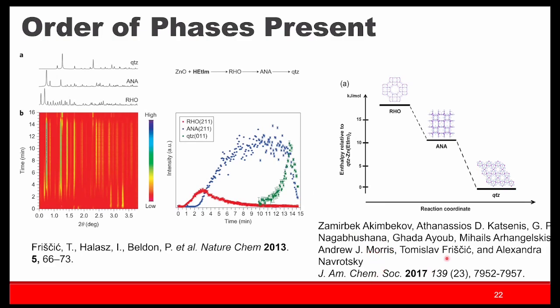And we did a bunch of calorimetry and thermodynamic calculations, which basically show that we're actually going down in energy. So we're starting at the least stable phase. So you can think of this as the kinetic product, and we're basically going down the energy ladder into the thermodynamically favored product. And so this is a way of rationalizing a lot of the behavior that we're seeing. We're not somehow defying thermodynamics or doing anything crazy here.